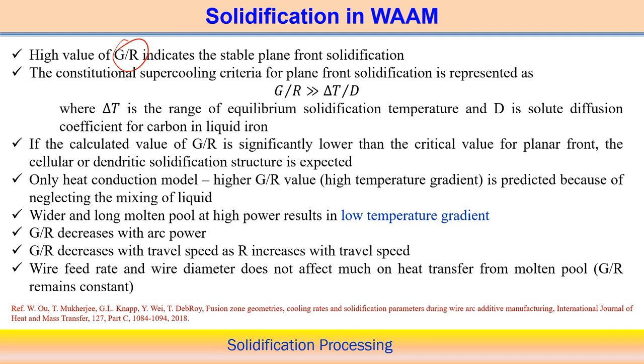When the planar front is not stable, there may be constitutional supercooling at the planar solidification front. Constitutional supercooling is very low when a stable planar front prevails — meaning G/R is very high compared to the ΔT/D ratio, where this ratio indicates the amount of constitutional supercooling.